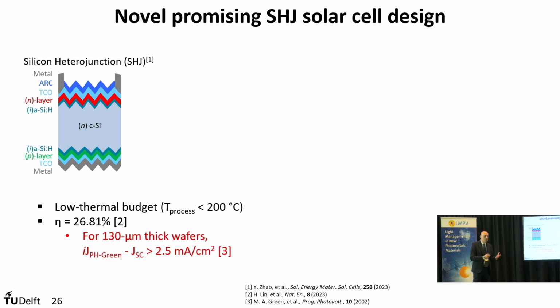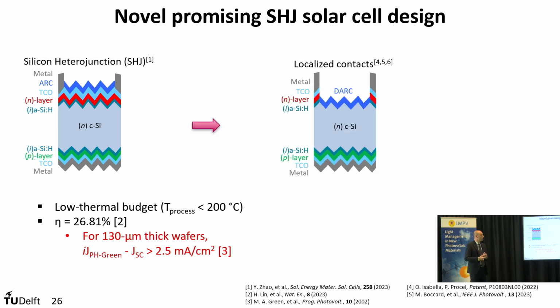But aside from going into very aggressive nanotexturing, which would prove challenging for keeping good passivation, what we would like to propose is a new type of solar cell architecture. We call it localized contacts, where essentially we keep the N-type layers only under the metallization, keeping the rest of the device completely open for receiving light. Essentially pretty much like a kind of local IBC device. Now, this is something that we want to optimize, but we have also started to work on it from an experimental point of view.